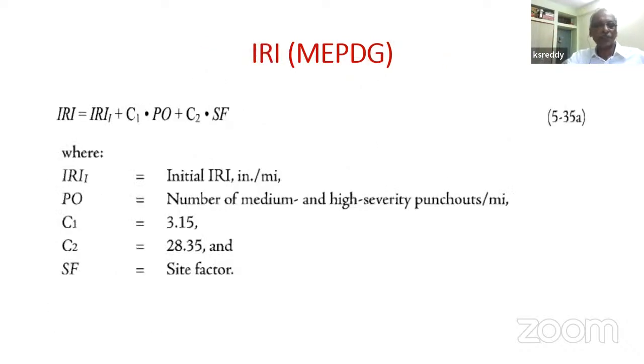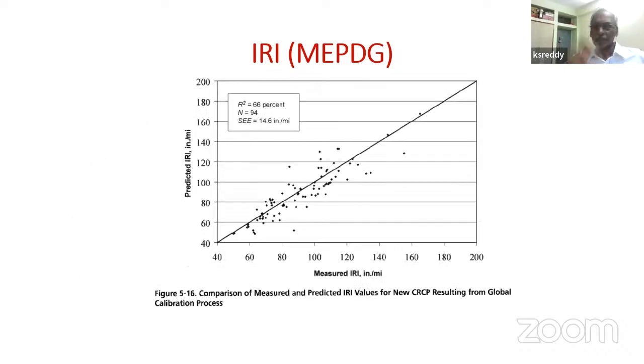And once you have all that information, in terms of damage index, punch outs, and other problems related to the cracks, you can put them in your IRI equation, which is your roughness or comfort. This is a comparison of predicted IRI with the measured IRI.